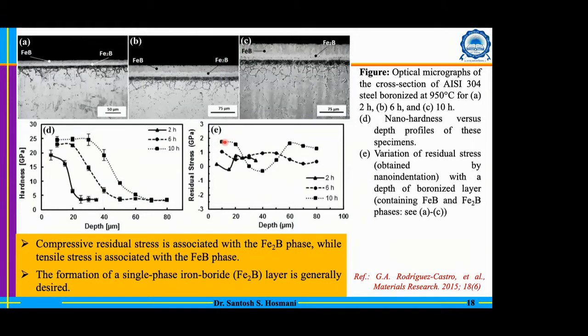Here they have studied at a constant temperature for different times. You can see that initially, at 2 hours, the FeB layer also has almost a compressive residual stress. Some compressive residual stress is there. However, as the time progresses to 10 hours, the residual stress nature actually changes from compressive to tensile in nature. And that is happening because of the growth of the boride layer.